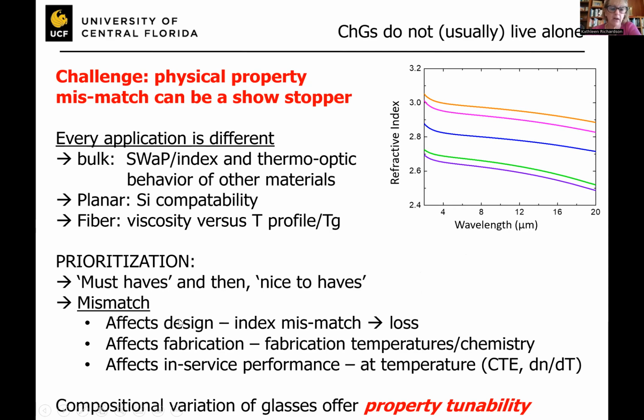And this mismatch affects how you design, because in most cases, if we're making optical materials or optical glasses, mismatch gives rise to loss, either absorption loss or scatter loss. It dramatically can impact fabrication. And it can affect longer-term in-service performance, because depending on whether the material is at static temperature, cycling temperature, ambient lab conditions, or flying in space, you need to understand that far-out application to understand how we can prioritize the properties that we want our material to have. Okay? The key takeaway here is the fact that we know what the knobs are. We can tune our material for those applications to hit the must-haves and do our best to give our customer the nice-to-haves.